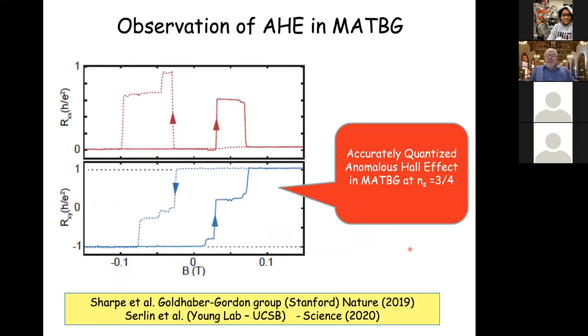Now, if you take that story and you allow different filling factors for different flavors, then if you have insulating states at odd filling factors, then you necessarily have different occupations. You occupy these topologically non-trivial valence bands, for example, differently for one valley versus the other.